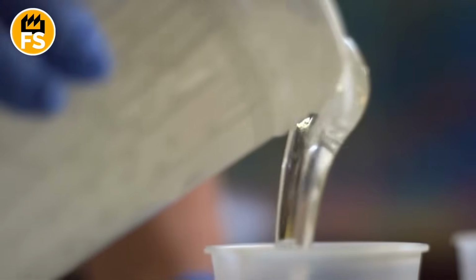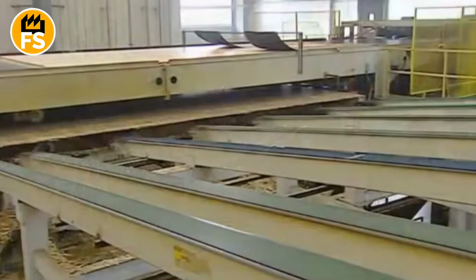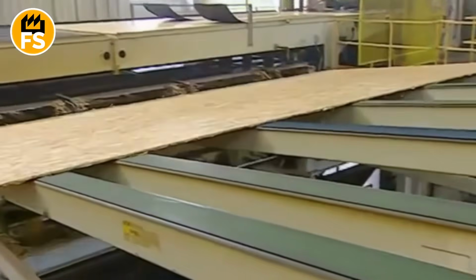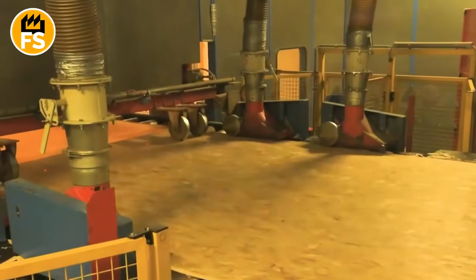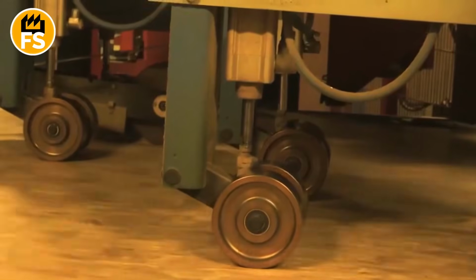This heat activates the resin, causing it to polymerize and permanently glue all the chips into a single monolithic shield. The wax also melts, even better impregnating the wood and filling microscopic voids. In a few minutes, the loose mass turns into a hard, incredibly dense, and hot panel.